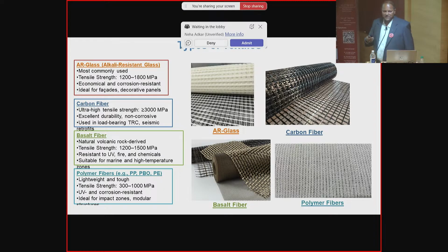So one thing that we need to understand is, in the case of a steel bar, the destruction of steel is due to corrosion, either carbonation induced corrosion or chloride induced corrosion. Whereas in the case of these glass fibers, the failure mode is by a method called alkali silica reaction. These glass fibers have a lot of reactive silica, because they are manufactured from silica sand, which is heated to 1200 degrees and suddenly cooled. So this contains reactive silica.